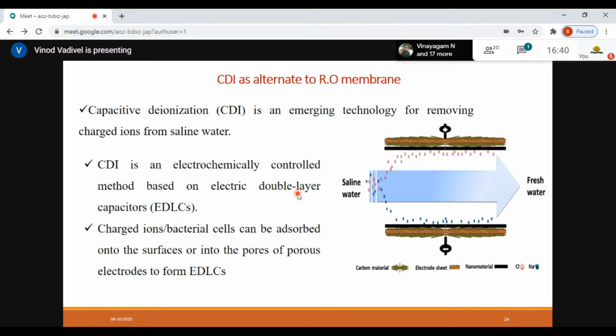It's an electrochemical system with electric double layer capacitance. It's mainly focused on absorbing charged ions and bacterial cells. When you have charged ions like sodium chloride, Na plus and Cl minus, what happens when you pass this saline water into this system? You have your nanomaterial sheet followed by carbon materials and electrode sheets, so you have different electrically charged barriers. In this system, the chloride goes to one side and sodium to the other at a particular potential, hardly 1.2 to 1.5 volts. It's a very low potential. And when you reverse this voltage, you can discharge these ions and reuse this material. So it's continuous, you can keep using this.